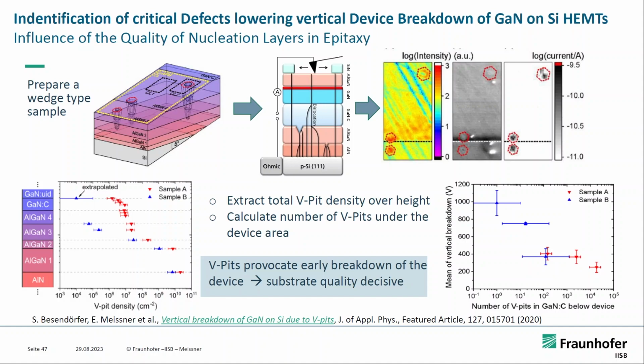And now we sliced it, and we saw in many SEM pictures - I won't show all of these - that there were at the edges little V-pits, and this is a function of the quality of the nucleation layer. And these V-pits are collecting impurity elements or dopants.